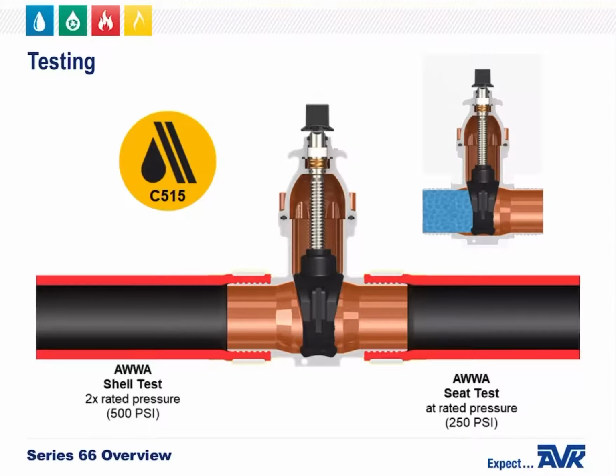Although this valve is rated to a working pressure of 250 psi, most waterwork applications operate at 50 to 80 psi. So in addition to seat testing this valve at the rated working pressure as required by AWWA C515, AVK performs an additional seat test at 30 psi. AVK performs this additional seat test to ensure that the valve maintains a leak-free, tight seal even at low pressures.